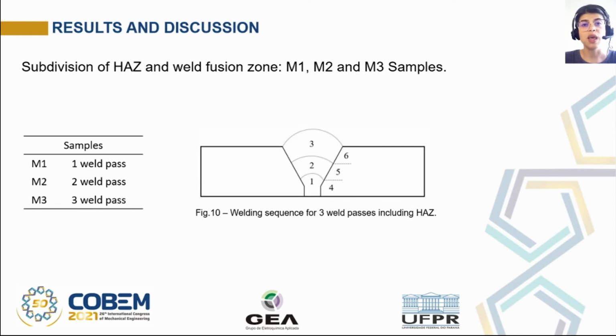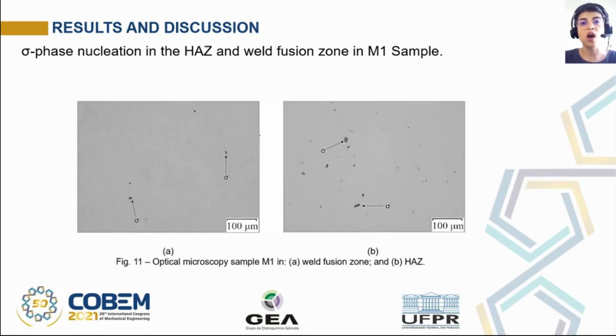In our experiments, we used three types of samples, which are M1 that had one welding pass, M2 that had two welding passes, and M3 that had three welding passes. Figure 10 shows the welding sequence for three welding passes, including the heat-affected zone. We can see the first welding pass, the second and the third welding pass, and the HAZ. Figure 11 shows the optical microscopy of sample M1, and in letter A is presented the weld fusion zone, and in letter B we have the heat affected zone. As we can see, the HAZ presents more sigma phase than the weld fusion zone.